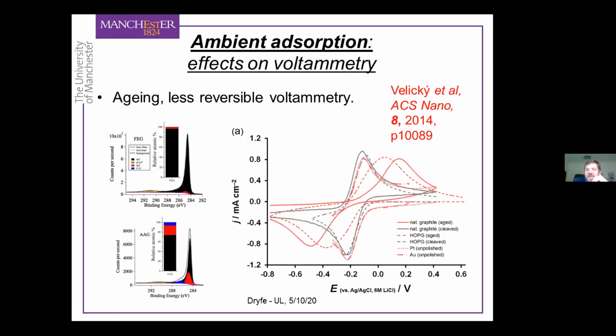So all this is to say that graphite is susceptible to contamination in aqueous and indeed in air environments. And those contamination effects show up in the wetting behavior and also show up in the voltammetric behavior. And again, now we can move on to some of our own data, which is entirely consistent with the work that I mentioned from Pat Unwin's group.